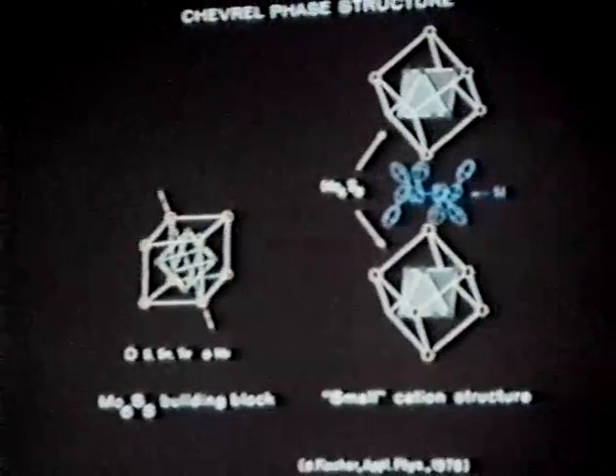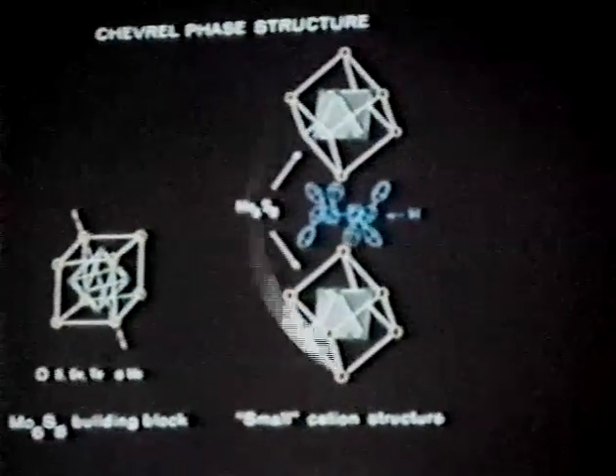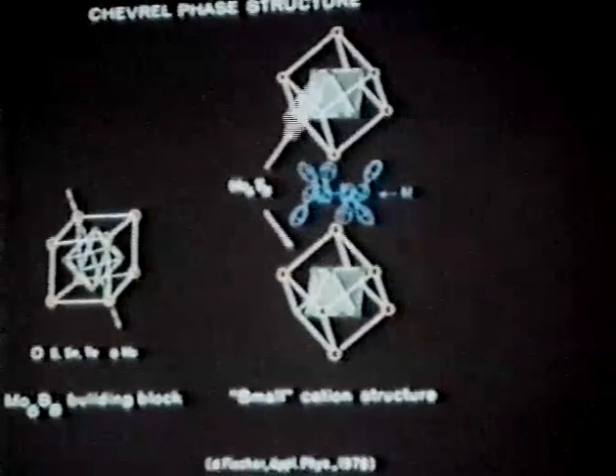This, again, then emphasizes the fact that these are really reduced molybdenum sulfides, and you can see this in the XPS data. You can confirm that all of these molybdenum oxidation states here are considerably lower than what you have for MoS2. Now, when you start to build up small cation, intermediate cation, or large cation materials, you can arrange these Mo6S8 clusters in various ways.